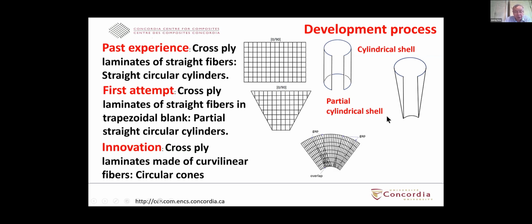So how to get a cone? Basically, the way we do that is that we use curvilinear fibers. Here we curve the fiber along this kind of direction, and we also have another kind of fiber along the radial direction. So you have the curvilinear fibers and radial fibers, and from this you obtain the shell structure, in the sense that the curvature at the top is not the same as the curvature at the bottom. You have a bigger circle at the top and a smaller circle at the bottom. So basically that is the idea in terms of making the conical shells.